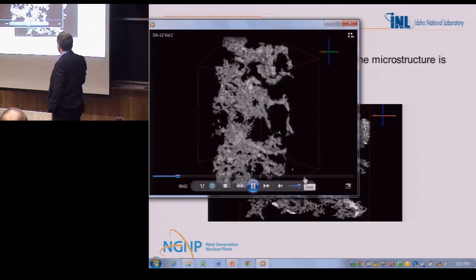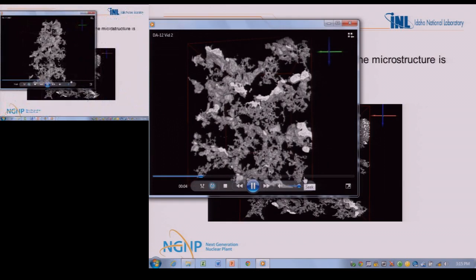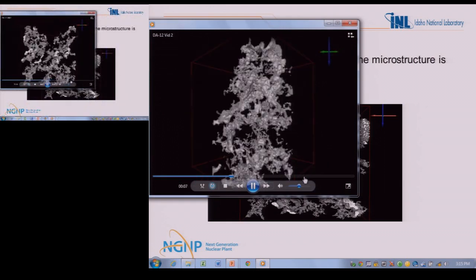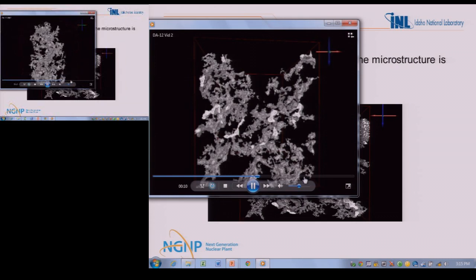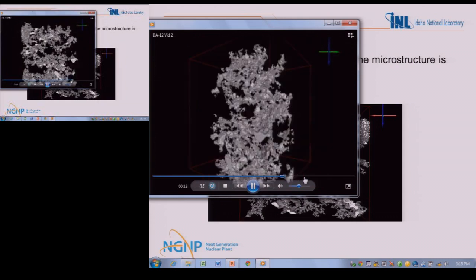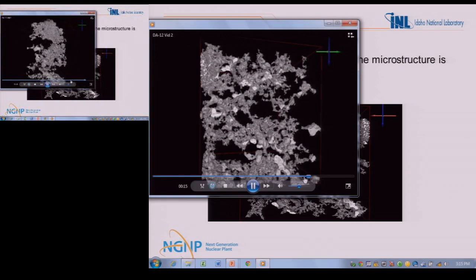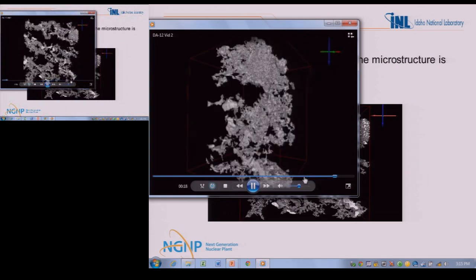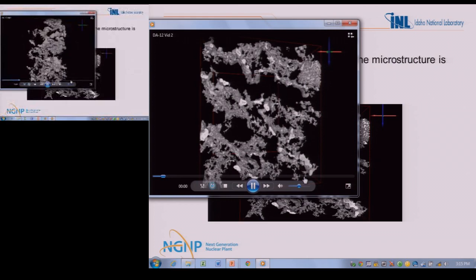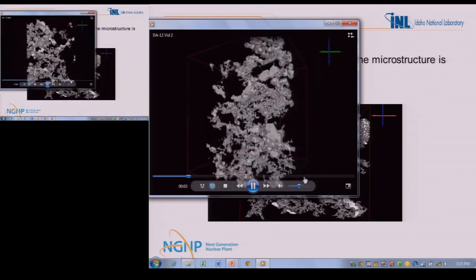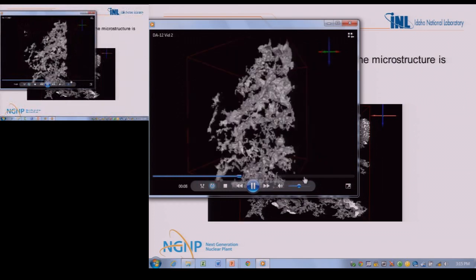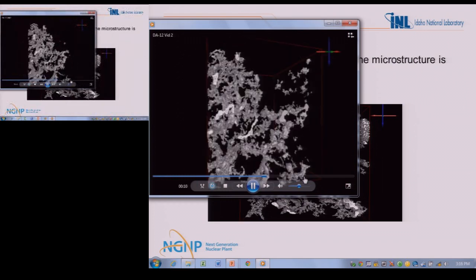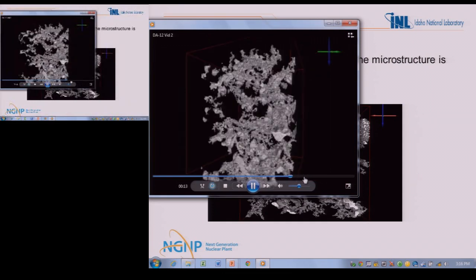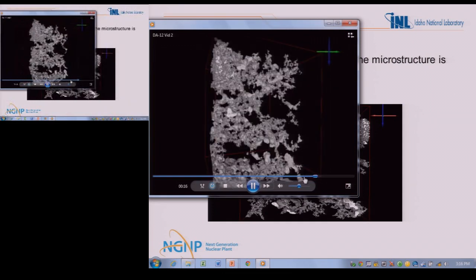Okay, let's see if this works. Oh, technology. Thank you. So this is some work that we're doing at the INL where we're looking at X-ray computer tomography. Alex, so what we're looking at here is one gigantic pore inside of about a 3 by 4 millimeter sample. It looks like it constitutes a huge amount, but remember this is three-dimensional on a two-dimensional plane. So what you're looking at is actually only about 7 to 8% of the total volume. But it's all one interconnected pore. Think about that if you're trying to produce a crack through it. That's easy because of the connectivity.